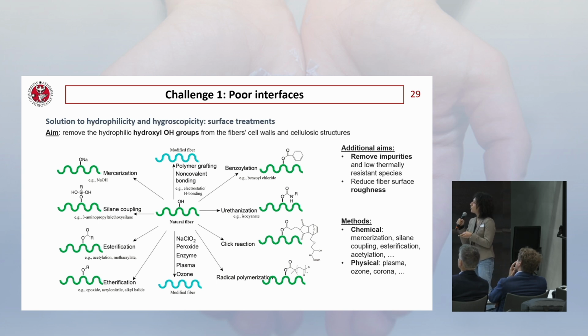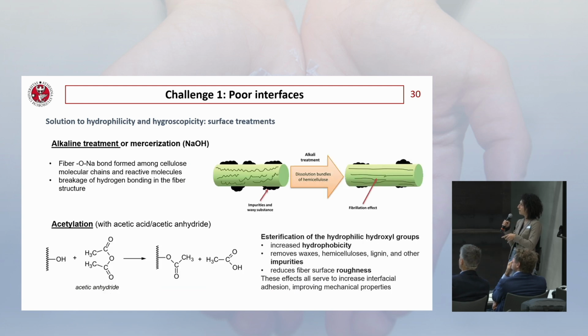What can we do? We can tackle this hydrophilicity and this hygroscopicity by surface treatments. The aim is to remove the hydrophilic hydroxyl groups from the fibers and to replace them with something else. For example, we can have chemical methods like mercerization, silane coupling, esterification, acetylation, etc. Or we can have physical treatments like plasma, ozone, corona treatment, etc. Two of the most important chemical treatments are the alkaline treatments, so treatment with NaOH, for example, and the acetylation, so treatment with acetic acid or acetic anhydride.